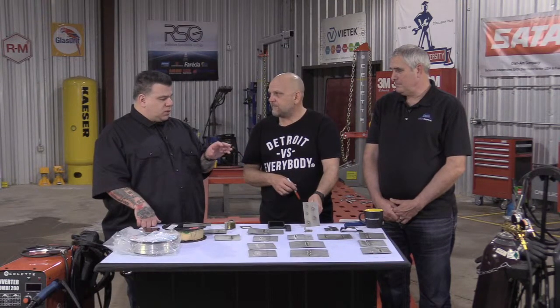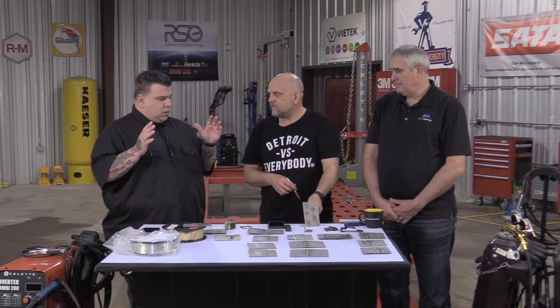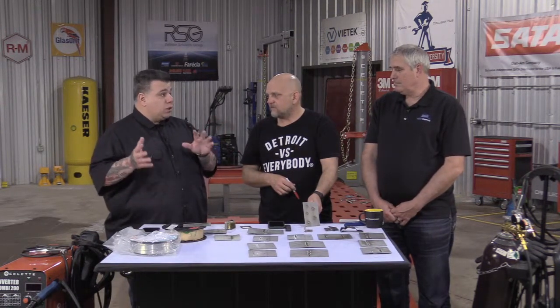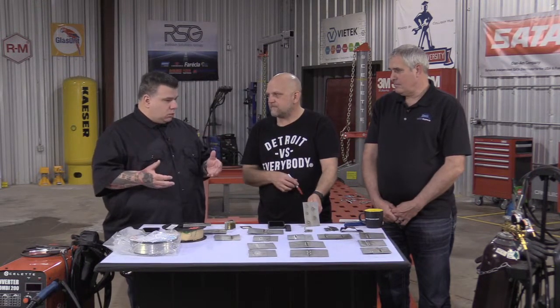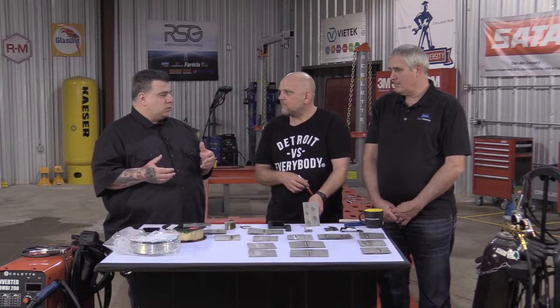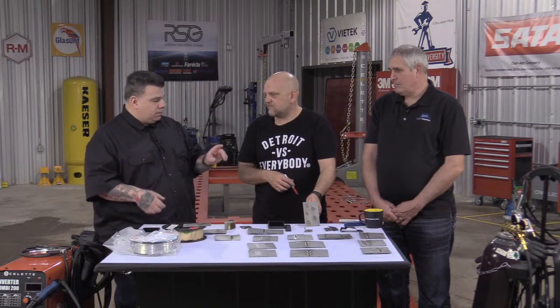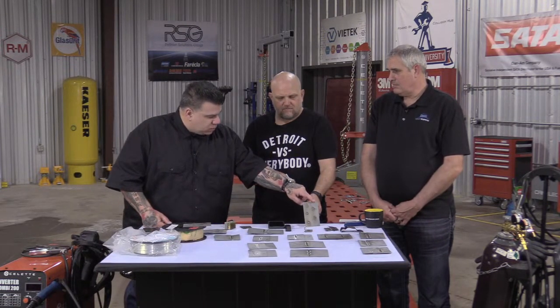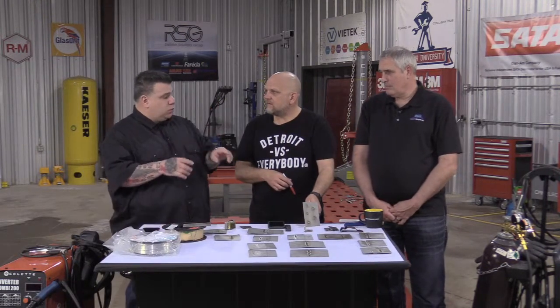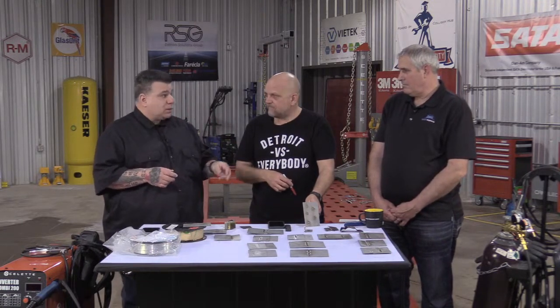Yep. So this is the issue that a lot of shops don't understand. When you're welding outer body panels and most unirails on unibody cars, you're welding with 0.6 millimeter, or 024, 025 wire. It's all 0.6 millimeter. That's what you should be welding with. The machine will work better at that lower grade with that thinner material. Had you had 0.6 millimeter or 024, this would probably not be as high and would have come out a lot smoother, and you'd be a lot happier with both the welds, not just the one weld.